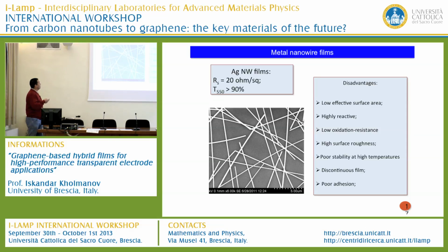One is reduced graphene oxide integrated with metal nanowire films. This is the SEM image of the silver nanowire films. The metal nanowire films have very low sheet resistance. It's better than ITO film. So TCF characteristics are better than ITO, but there are several disadvantages that limit the application of silver nanowire or even any kind of one-dimensional nanowire films.